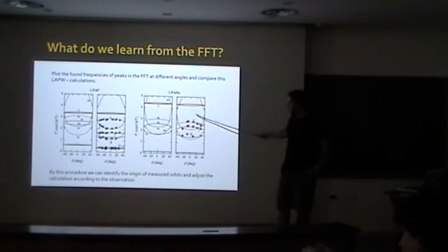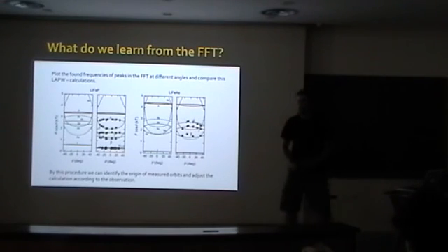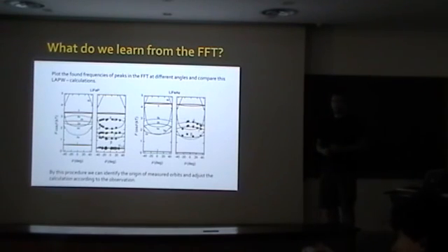But we're measuring bulk here, so we're not sensitive to this surface effect, and we see that this material is actually neutral in terms of electron to hole volume, and they see it's hole doped. So I think we have some pretty good arguments there. So you think it's a sample problem?